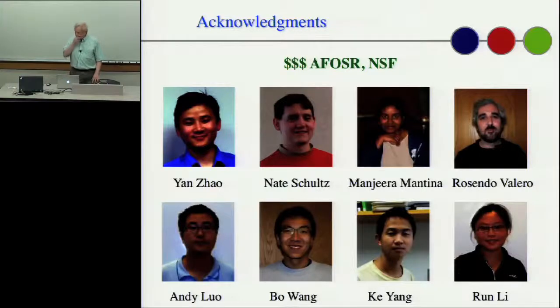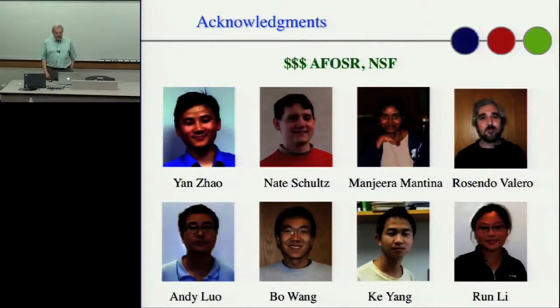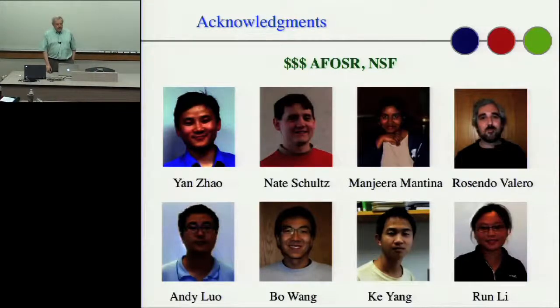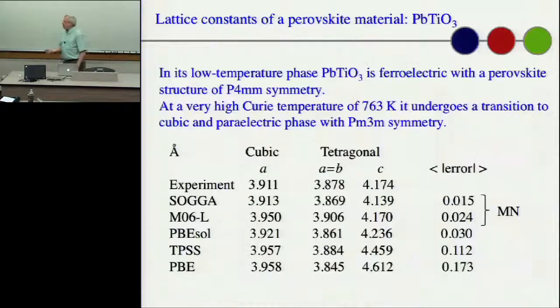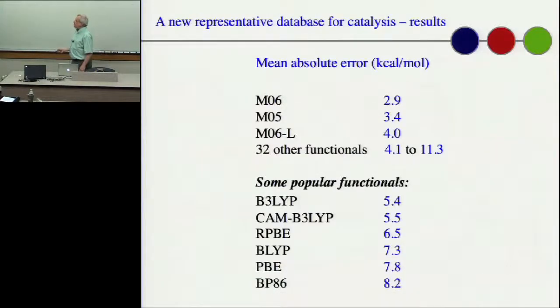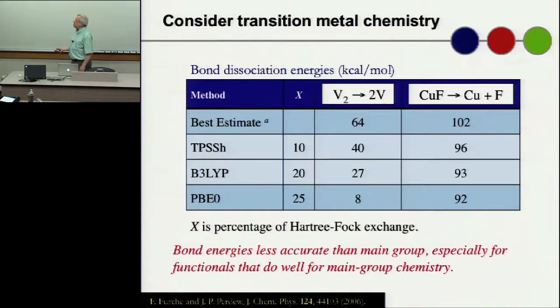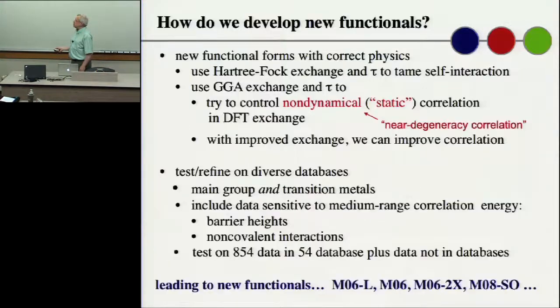So one notorious problem for local density and generalized gradient functionals, but particularly the local ones, is that they do badly with hydrogen bonds. And you didn't really mention hydrogen bonds, like non-covalent interactions, like in the water dimer? Yes, that kind of hydrogen bond. You didn't really mention any testing of that. Well, that one database had non-covalent interactions, and that includes a large number of hydrogen-bonded systems as well as dispersion-bound systems.